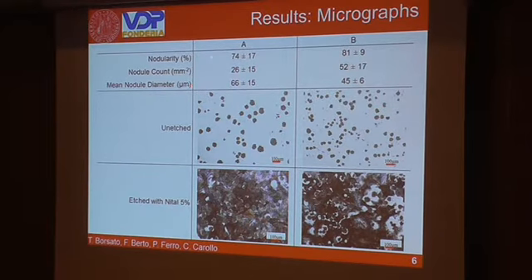We can see that the nodularity and the nodule count are greater for casting B than casting A, while the mean nodule diameter is lower. From the etched conditions, we can see that the matrix is perlitic, with some percentage of ferrite at grain boundaries and surrounding the graphite nodules. This ferrite was found slightly higher in the case of casting B, which was inoculated with bismuth.